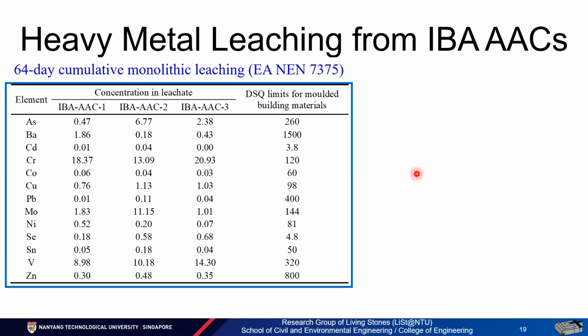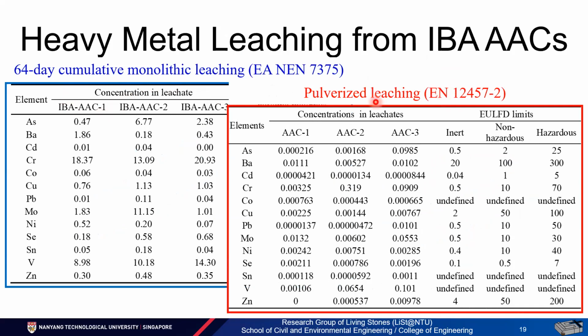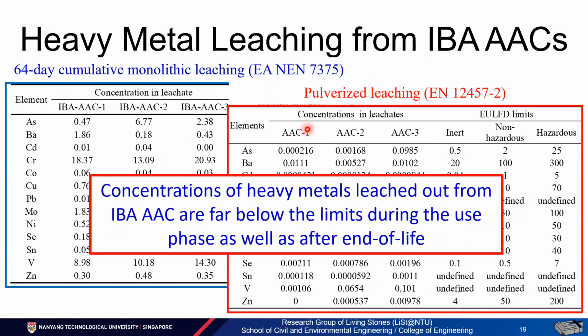The heavy metal leaching from the resulting IBA AACs clearly shows that both the monolithic leaching and the pulverized leaching are much lower than the standard requirements. So we can say the concentration of heavy metals leached out from the IBAC are far below the limits, both during the use phase (monolithic) and after the end of life (pulverized leaching).